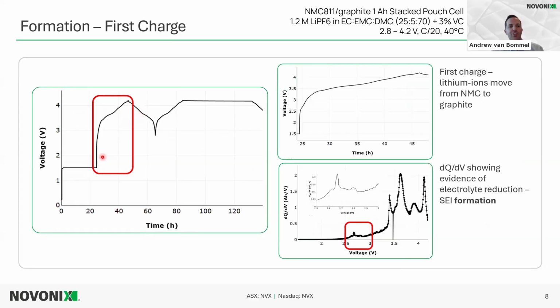And then I'm showing the first charge here as part of that voltage versus time graph. In that first charge, lithium ions move from the NMC to the graphite. During that, we can plot the differential capacity versus voltage, so dQ/dV. And usually we show this portion here between 2.5 and 3 volts. This is when you get reduction of certain species in the electrolyte. VC, EC are reduced, things like that, maybe different additives if you have different additives in your system as well. We can look at this and see if there's consistency between cells and look at different cells to see if we see the same reduction. Sometimes this can be changed depending on the salt present as well. So we look at this for evidence of that reduction, and this is evidence of that SEI formation, that solid electrolyte interphase, and that's why this process is called formation.